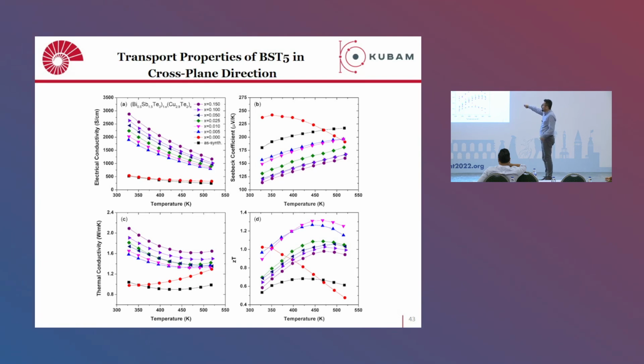And the Seebeck coefficient, in a similar manner, is high because the carrier concentration is probably low here. As you increase the copper telluride amount, the carrier concentration, probably through copper doping of this material, gets higher, and the Seebeck coefficient gets lower. Thermal conductivity, of course, since it's a metallic material, means metallicity actually increases the thermal conductivity as well. Okay? Let's see the overall effect.